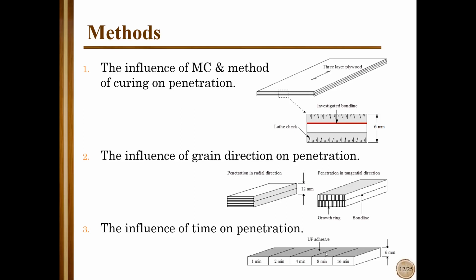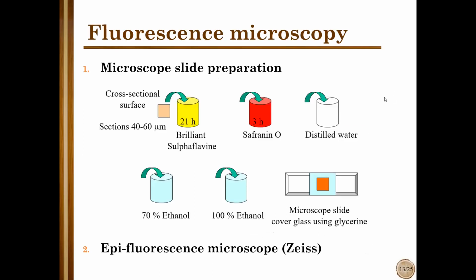There was no application of pressure, and of course penetration was much smaller than in the case of samples bonded in the hot press. In this part, we used fluorescent microscopy. The main challenge was how to prepare microscopic slides to see something under the microscope. We used sections with thickness 40 to 60 micrometers, I'm sorry. Especially with plywood we had some problems because plywood is much more fragile with a lot of cracks, so we had to take a thicker sample.